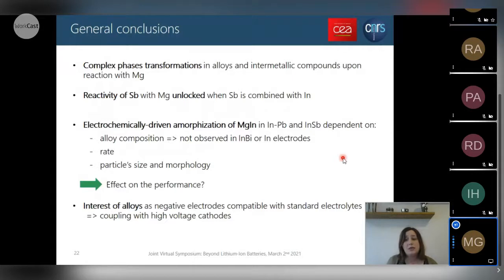In both InPb and InSb, we showed a peculiar electrochemical-driven amorphization of the MgIn phase that really depends on the alloy composition, because this is seen here in InPb and InSb alloys, but was not observed in the literature in pure indium electrodes or indium bismuth electrodes. And in the case of InSb, this amorphization depends on the rate and also on the particle size and morphology of the starting material.